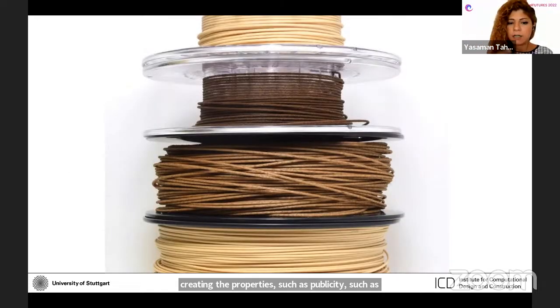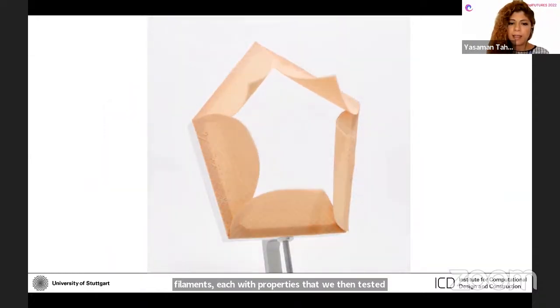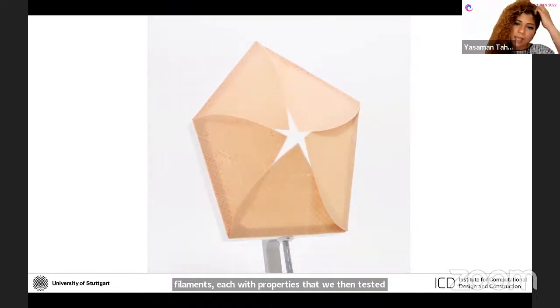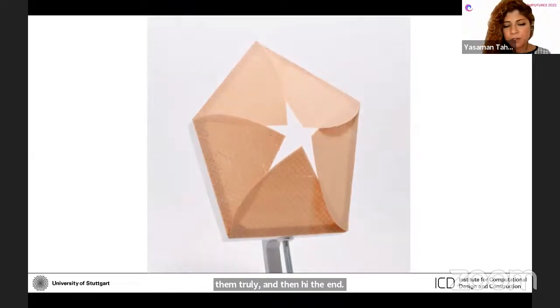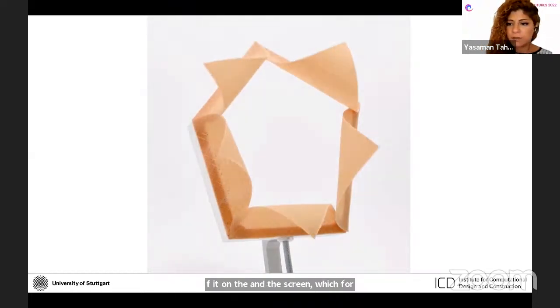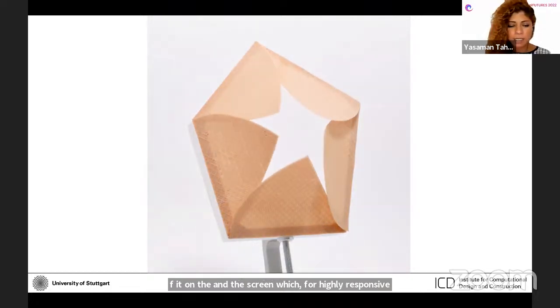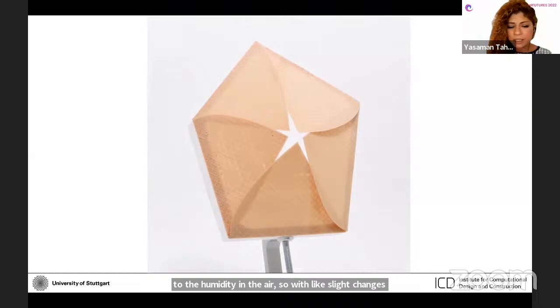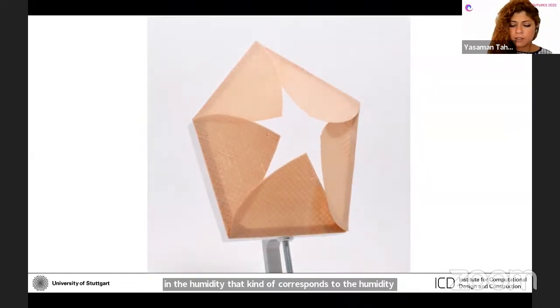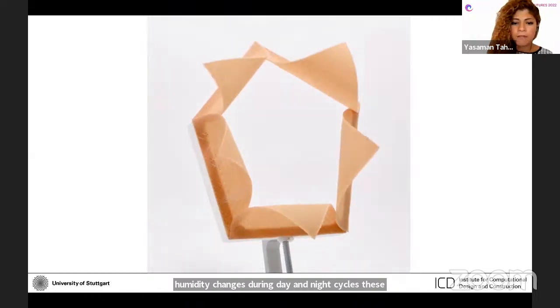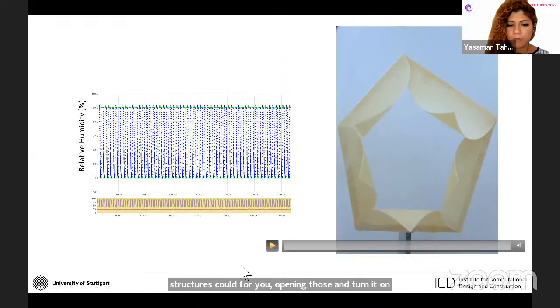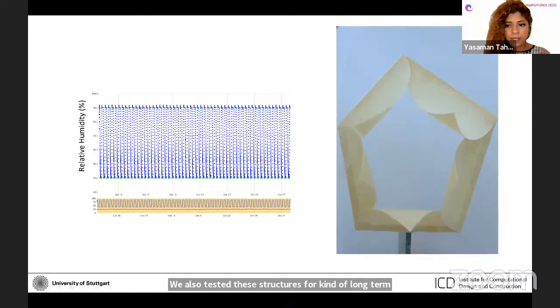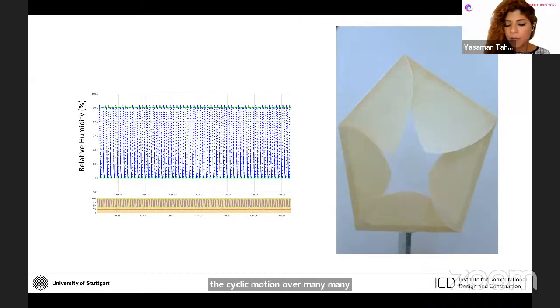And then this led to the creation of a palette of different filaments, each with different properties, that we then tested thoroughly. And at the end, it let us create structures, as you see one example of it on the screen, which were highly responsive to the humidity in the air. So with slight changes in the humidity, which correspond to the humidity changes during day and night cycles, these structures could fully open and close. And further on, we also tested these structures for long-term performance to see if they can perform the cyclic motion over many cycles, such as a pine cone can do.